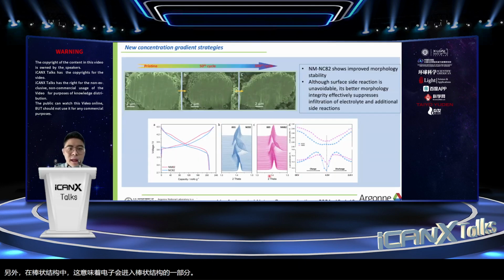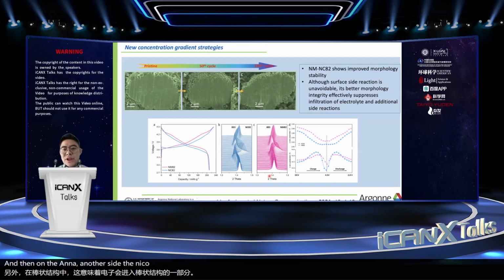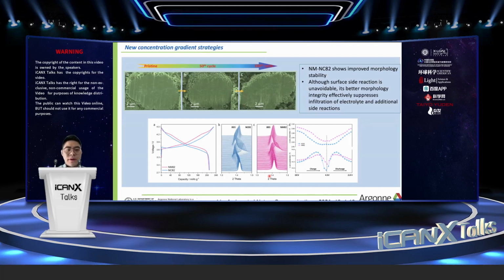And on the other side, the nickel manganese–nickel cobalt design shows much better morphology stability. Look at these three particles over 100 cycles. We didn't see any particle cracking inside the bulk, right? So that means the electrolyte cannot get inside, and then we suppress the surface reactions.